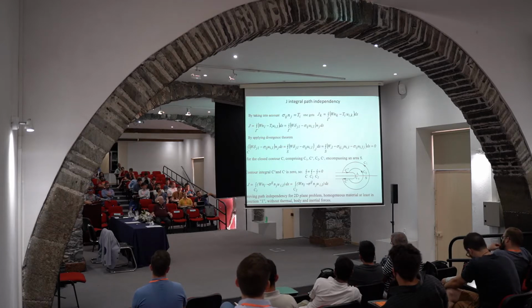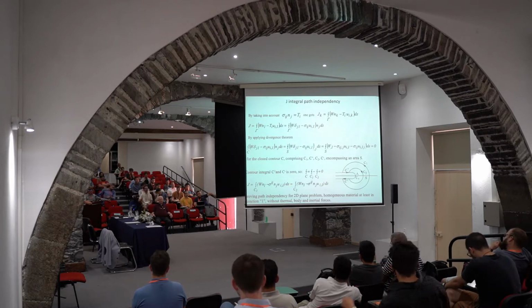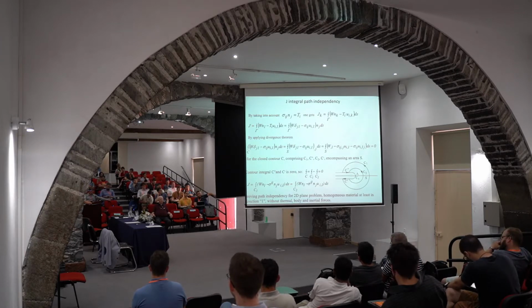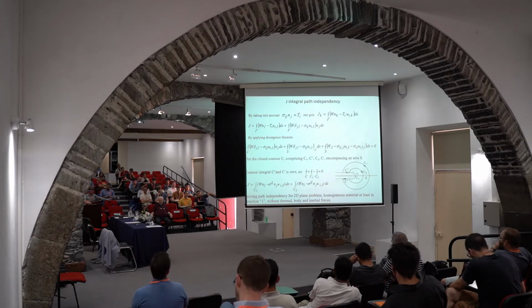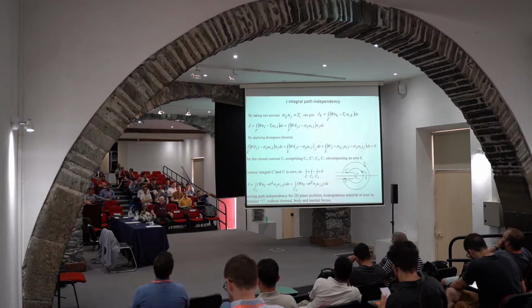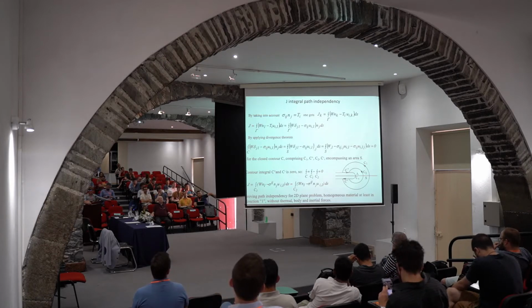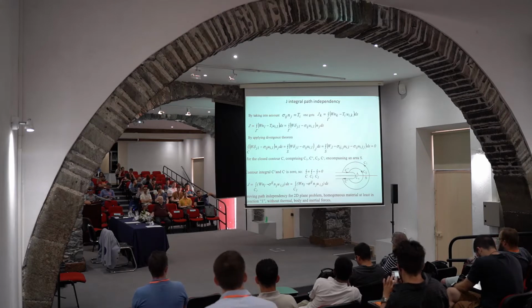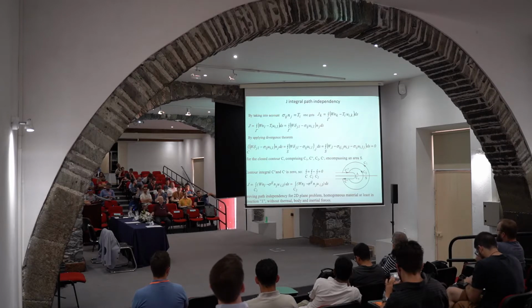So this scheme at the bottom to the right, with C1 and C2 as two paths around the crack tip, we can prove that the J integral has the same value for both of them, because on the parts C minus and C plus, the J integral is actually 0. This is of course a path which contains or encompasses the crack and crack tip. Otherwise, if there is no crack on this path of the J integral, its value is 0.